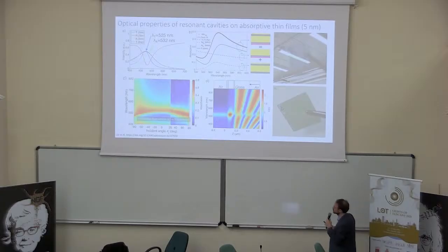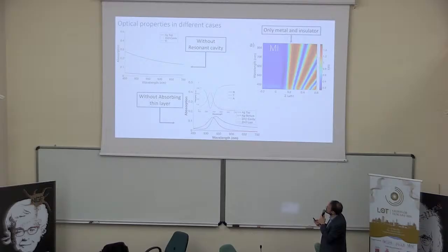This is normal for these materials, but with this particularity that it still remains transparent. And then, this is just to see again that if you do the structure without the thin titanium layer, you get a structure that doesn't reach an absorption higher than zero, and you get only reflectance and transmittance, and the reflectance goes down to zero.